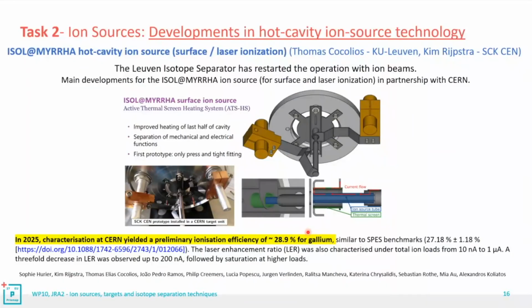You need to have an extremely high temperature in both hot cavity and transfer line, close to 2,200 degrees Celsius. A good example of thermal design is surely constituted by the ISOL@MYRRHA hot cavity ion source. In the first part of PRISMAP, they developed the mechanical design, studied this object thermally, and produced the first prototype for testing at high temperature.